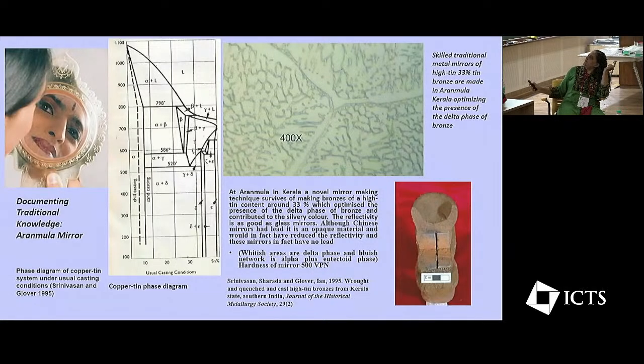So when we actually looked at the microstructure of a small piece of that mirror, as you can see, it's practically as good as a modern metal mirror. And here you can see that the structure shows the silvery white delta phase and a very fine network of the alpha plus delta eutectoid, because there's a little bit of alpha plus delta eutectoid also, which carries over into this, this is really where the alpha plus delta eutectoid range is. And this is what actually embrittles the bronze. So typically this should be very brittle and not very easy to cast.